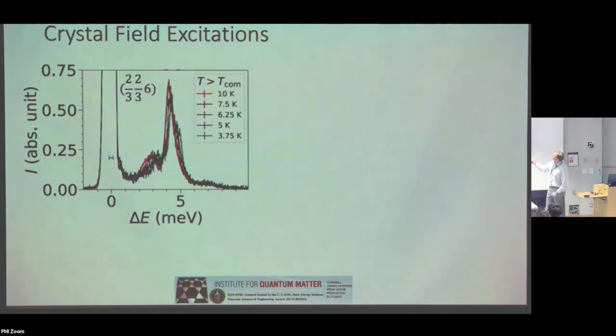And so this is what the excitations look like in the temperature above the commensurate phase transition. So first in the paramagnetic phase, this is with red, and so there's a kind of fairly broad peak, and then the second peak, these are kind of the main things which we would think of as the crystal field excitations. And first of all, you see that they lie in the energy range that corresponds to the Schottky anomaly in the specific heat. So that's as we expected. And that's how we knew to use that instrument. We knew that would be the range. And then as you cool down, there are some shifts that take place, but nothing very dramatic.